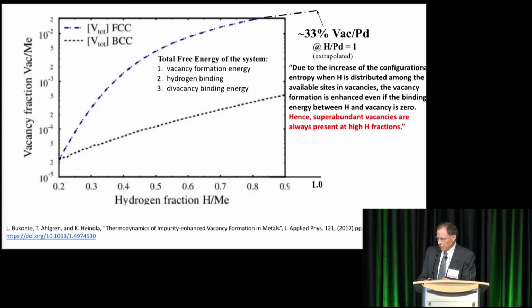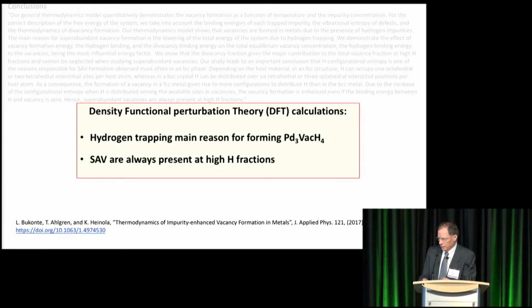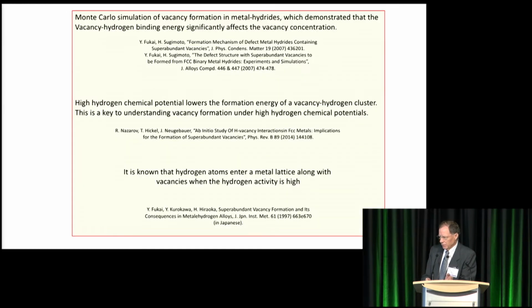Again, I'll have to go fast forward here. The theoretical density function perturbation calculations show this structure to be the most stable, and that there's in fact a bonding or trapping between the hydrogen and the vacancy, and that superabundant vacancies are always present at high hydrogen fractions. That's what the calculations show. That's what the thermodynamics show. Whether the kinetics are going to be in favor is another issue.